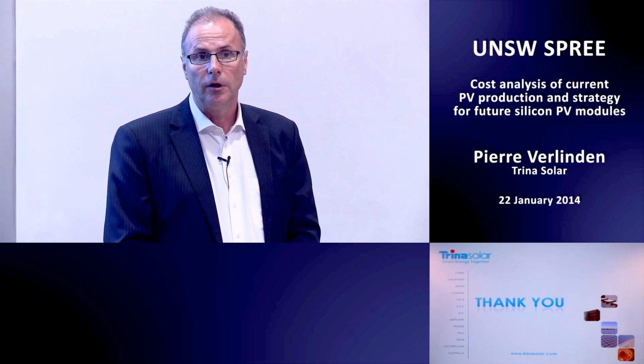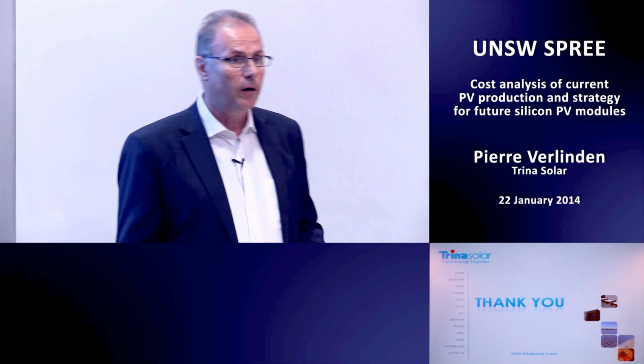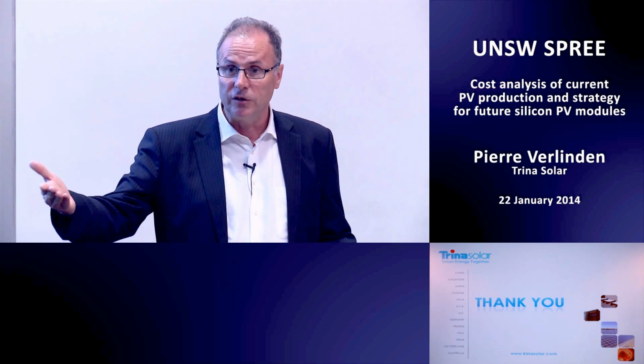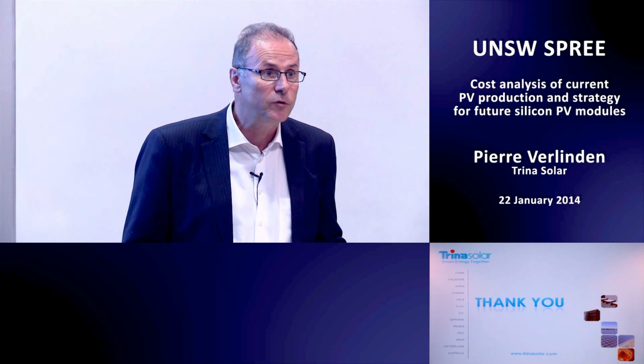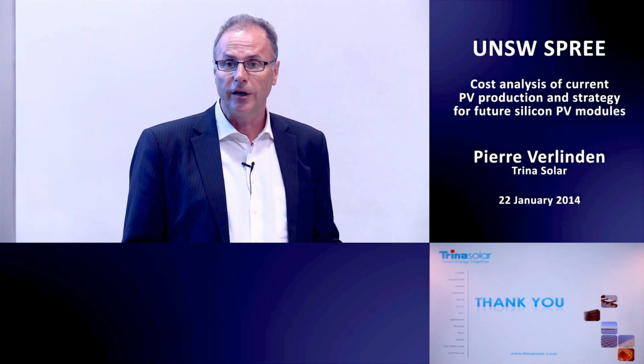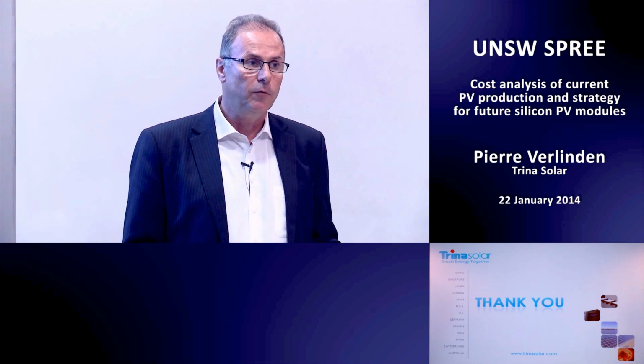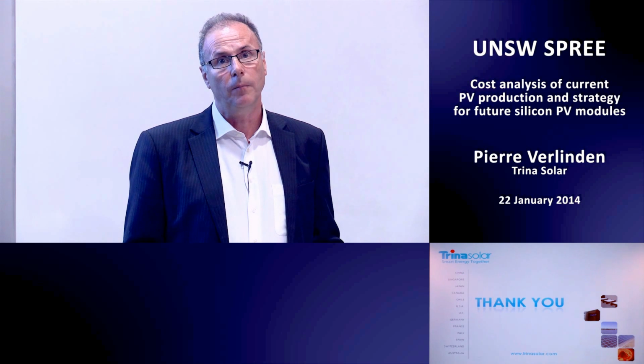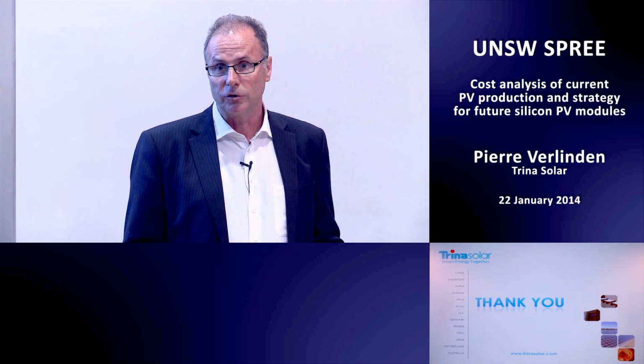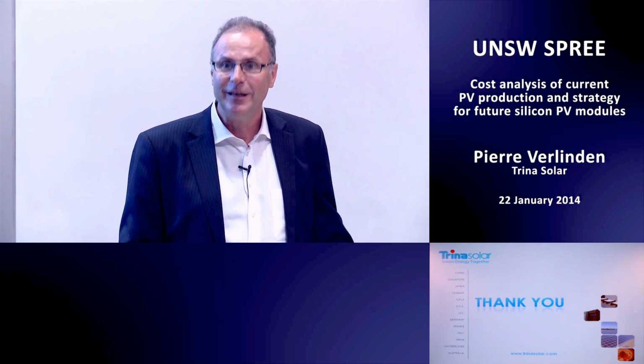With the double glass module, in the accelerated testing we've done in-house, we've done TC600, and we're doing TC800 pretty soon. We've done DH3000 so far. We've done humidity freeze up to 50 cycles. So we're talking 5 times the kind of testing that you do for IEC 61215, and we see much less degradation than a standard module. So our guarantee for a double glass module is minus 0.5% per year, or lower than that. Now, the question is, can you prove that with field data? Not yet. So that's the big question.